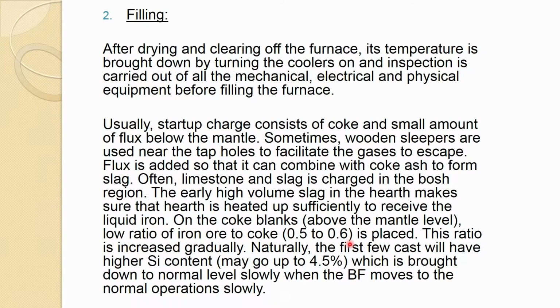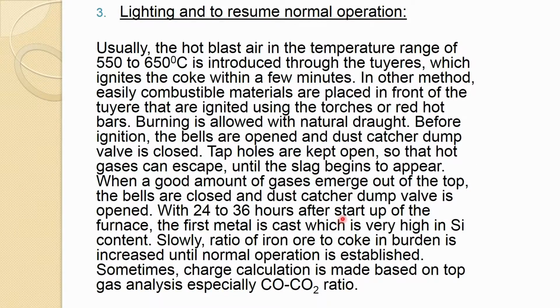is done in the blast furnace, and after that once you have packed it with ore and other things, then lighting. So, lighting and operation have been combined into one. During the starting we put it third and fourth, but here it is combined, but it does not matter, you can see the difference. So, usually the hot blast air in the temperature range of 550 to 650 degrees Celsius is introduced through the tuyere, which ignites the coke within a few minutes. So, when you are injecting that sort of high temperature blast air, naturally coke will ignite very soon. So, this is one of the methods.